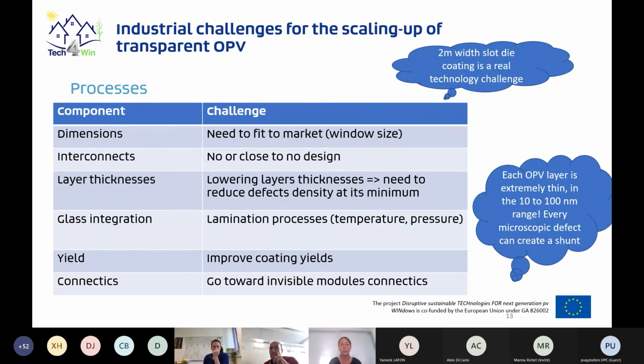Then for window application, we will need to make a glass integration of the different components of the window. So the products that we develop will have to undergo lamination processes to be laminated in glass, meaning that there are some constraints in terms of temperature and pressure, among others. Coating yields need to be improved to avoid any defect and any failure in the devices. And the last point is linked to the connectics. I'm sure there are other ones, but the connectics is also a challenge that has to be taken into account at the beginning of the project, because we will need to go towards invisible or really hidden module connectics.